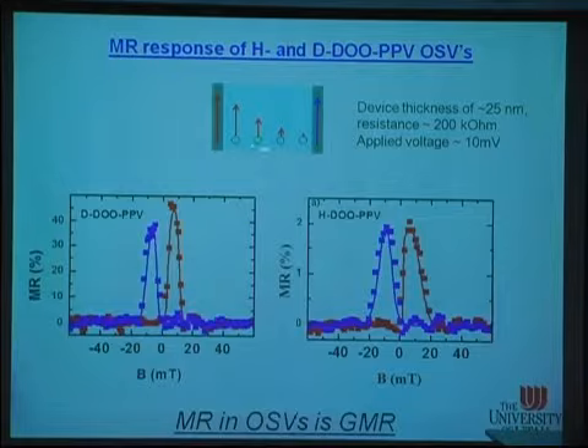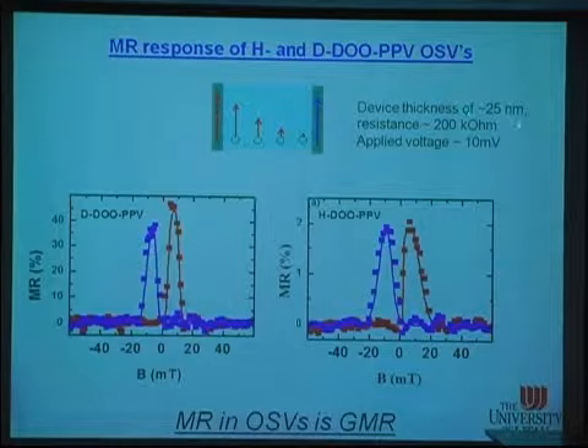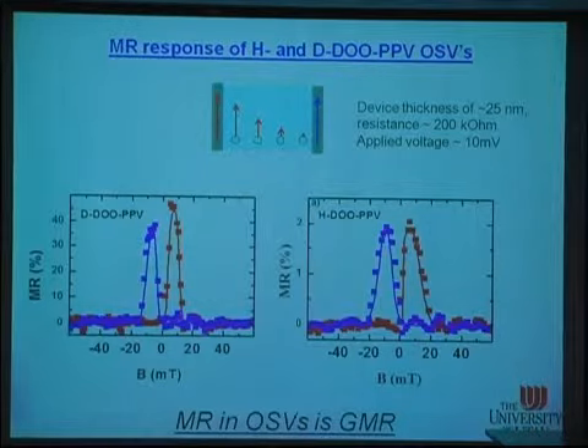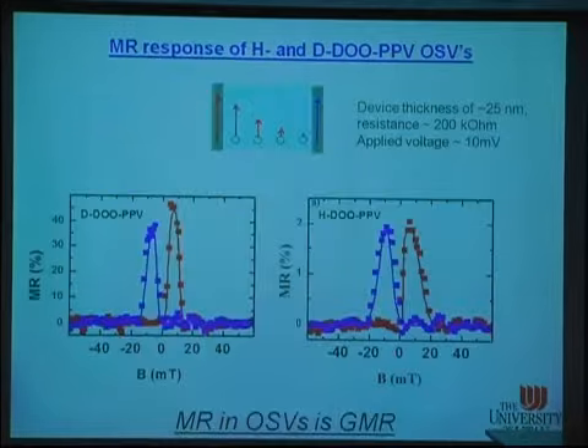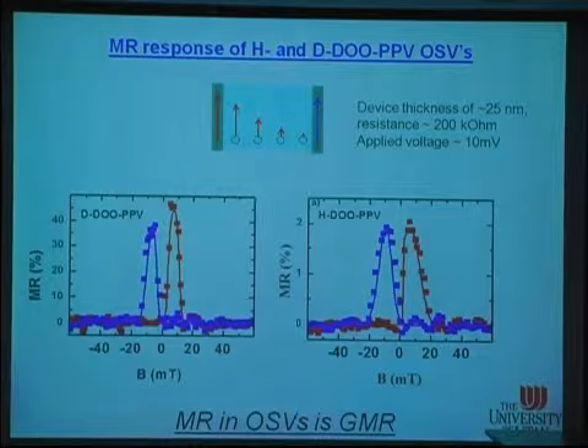You can see the spacer here, and we use LSMO and cobalt. The device is about 25 nanometers thick. The applied voltage is about 10 millivolts. Everything is identical, the same temperature. And here is the result. You can see the magnetoresistance in the deuterated D-DOO-PPV is 40%. On the other hand, the effect in the hydrogenated H-DOO-PPV is only 2%.